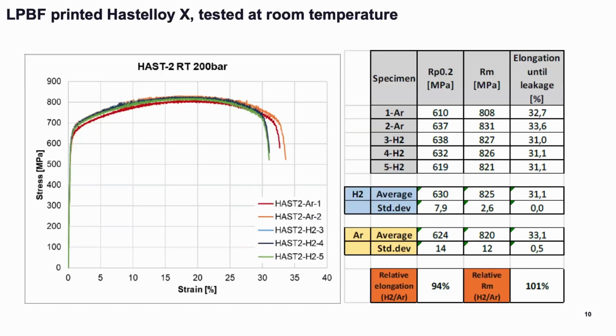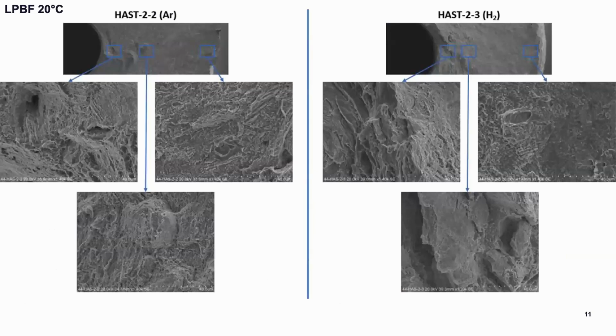For the printed Hastelloy X, we also see very small differences, with a relative elongation of 94%. And the fracture surfaces look very similar in hydrogen.